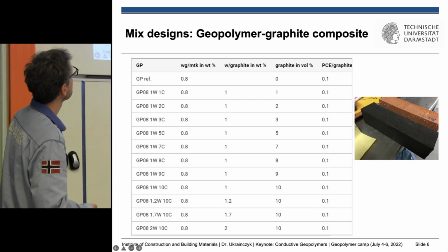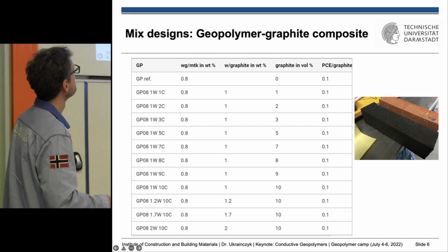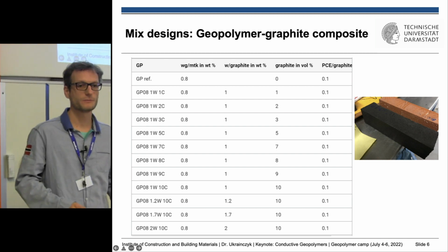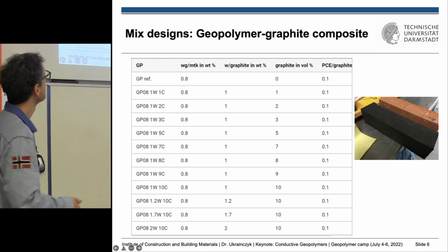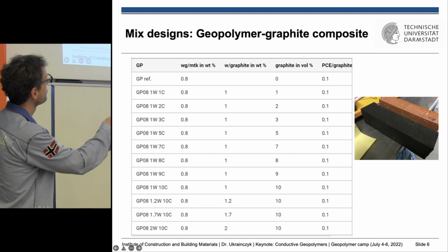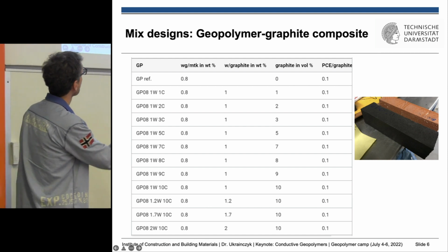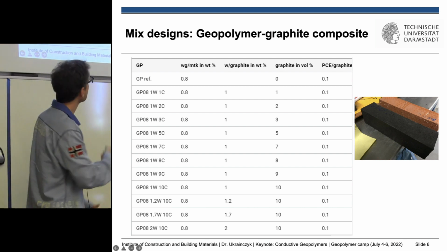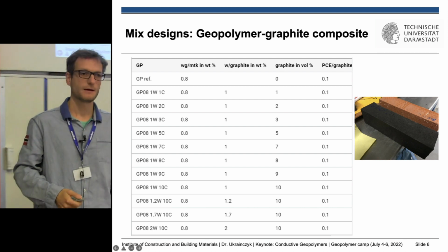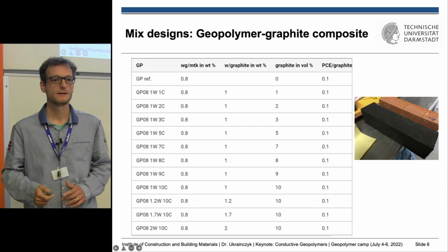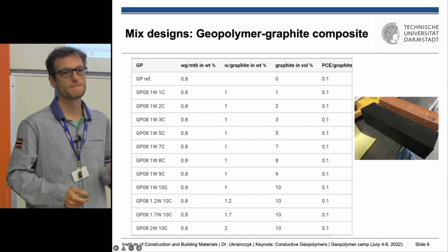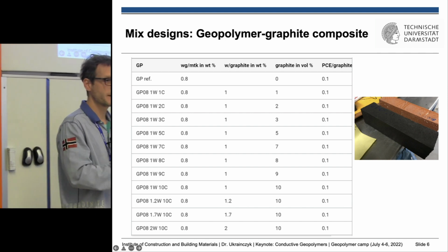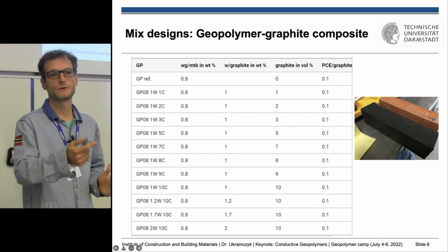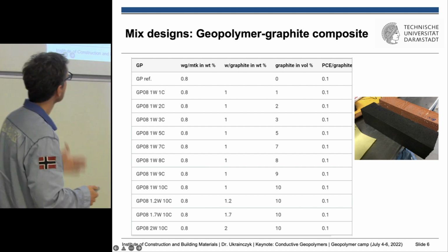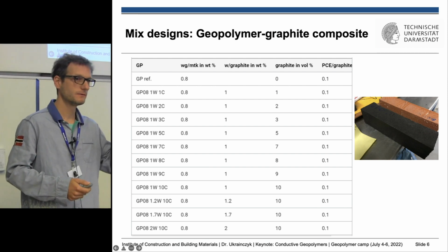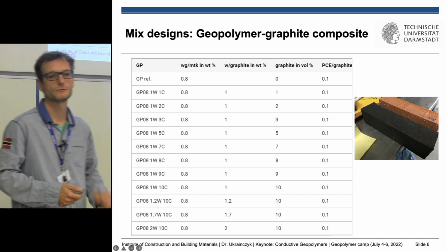So now the mix designs. We used different percentages of volume fraction of graphite, from 1 to 10, and we used the water glass to metakaolin ratio 0.8. I think it's maybe not too high, but the philosophy was to follow that if you have 50% of the metakaolin reactive, and to get this 1 to 2 ratio, that means roughly 0.8. But I think it's maybe still a bit overshooting, too much water glass.